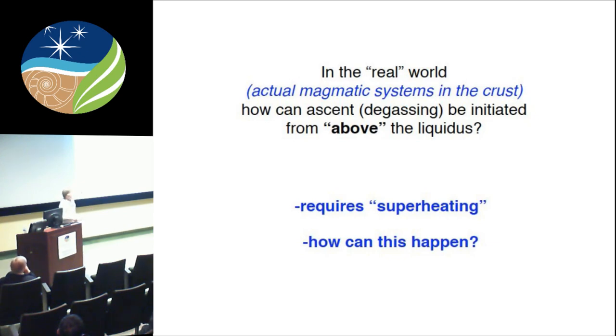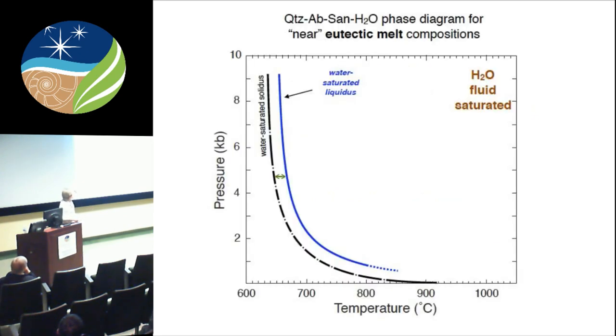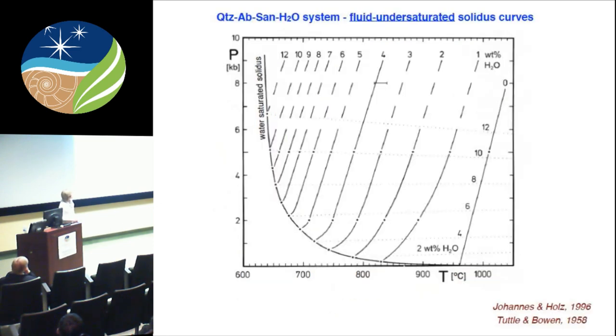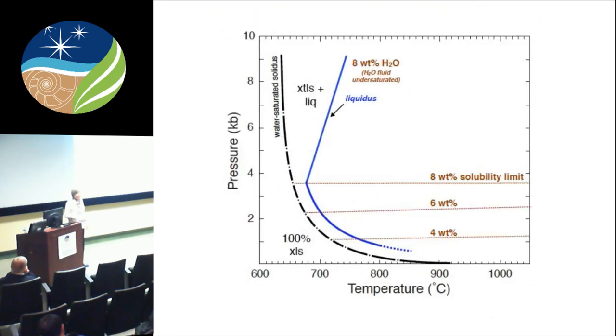Well, again, let's go back to this diagram. But let's imagine what happens to the liquidus surface when it approaches undersaturated conditions. So this is the pure system, but here's 8 weight percent water, and I'm going to superimpose that on this diagram. So imagine we have this near-eutectic composition with a total of 8 weight percent water. If we're deeper than, say, 4 kilobars of pressure, then it's going to be undersaturated, and the liquidus will now have a positive slope.